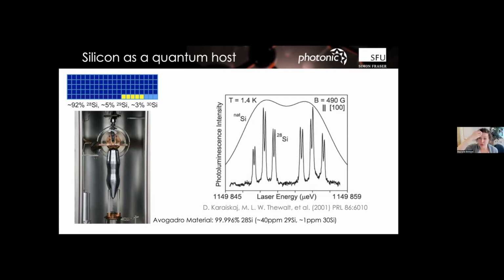So you'd think, okay, well, this is great. It looks like a good photon interface until you look at the quantum efficiency of these interfaces. And maybe that's why people stayed away from silicon. The quantum efficiency of phosphorus, of this particular optical transition, was really low. And a lot of that's attributed to the fact that it's an indirect band gap, but that's not the end of the story there. It just happened to be the case that this particular defect, and a lot of them, have really strong Auger recombination. For those of you who have gone through that condensed matter training, Auger recombination seems to dominate a lot of things. And I guess people just didn't bother going looking.